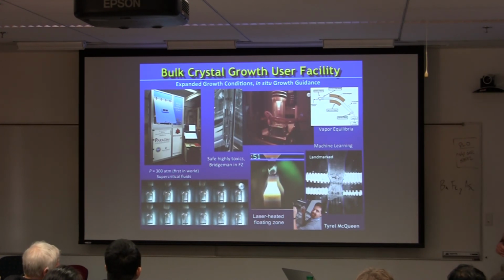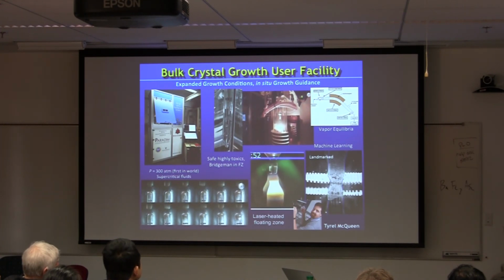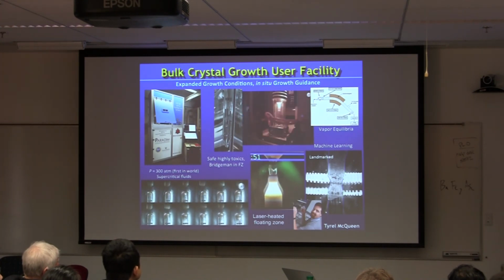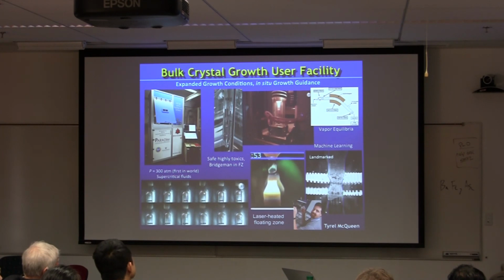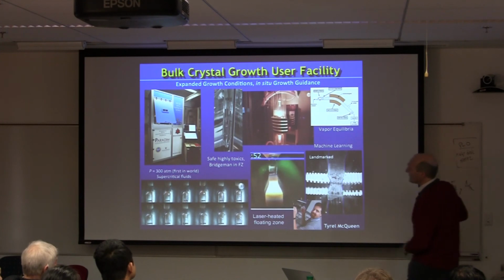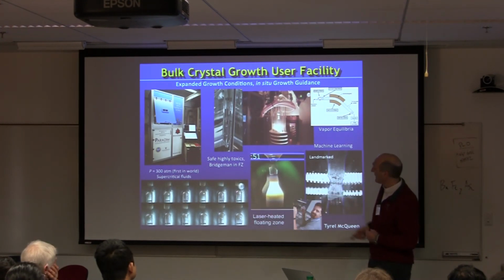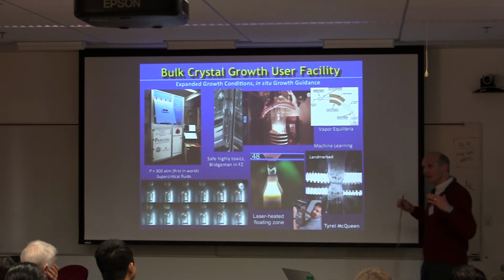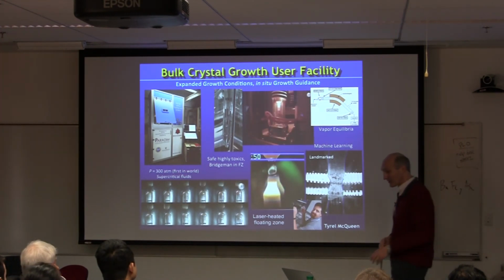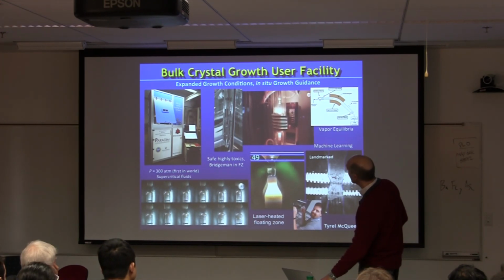And at that pressure, some of the gases become supercritical. So argon, carbon dioxide, oxygen all become supercritical, so that not only can you access these ground states that require pressure to form, but also the stability of the growth can become better when it's growing inside of the supercritical fluid. So here you see sapphire growing inside of oxygen at higher pressures, up to 300 atmospheres. Also laser tilt pedestal growth, induction heating. Okay, so high temperatures are possible in this facility.